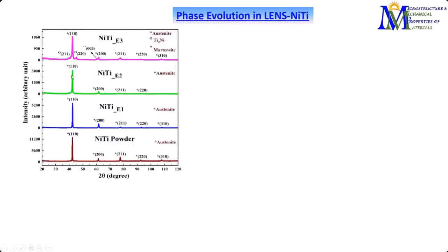Coming to the phase structures, we've seen that E3, as I said, develops some amount of precipitates as well as generating some martensite phase. As I explained, the pseudoelasticity or shape memory effect comes from the transformation of austenite to martensite. So the presence of any martensite actually hampers this process, and we end up having less recoverable strain in that case.